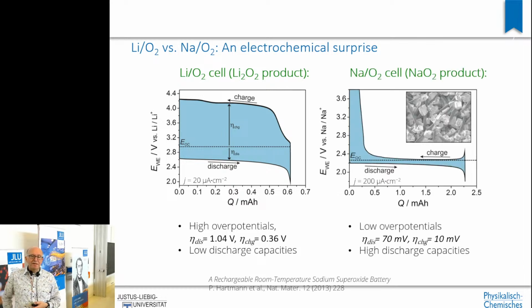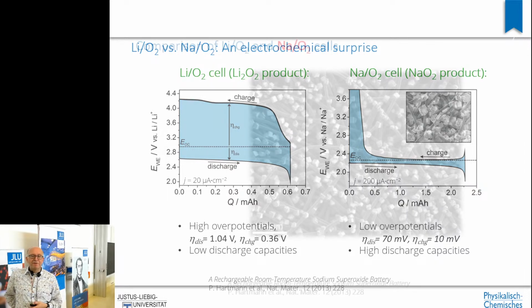And then a few years later, one of our PhD students, more or less by serendipity, found that if you do the same with sodium metal, sodium electrolyte, otherwise everything is the same, you see this blue curve, or this blue area, which is the loss of energy, gets rather small. You have very low overvoltage in both directions. And this is due to the fact that only one electron is being transferred to the oxygen molecule, and you get a superoxide. And this one electron transfer process in both directions works very well.